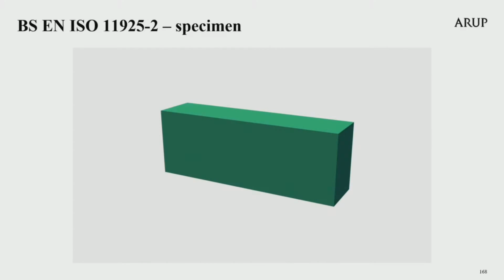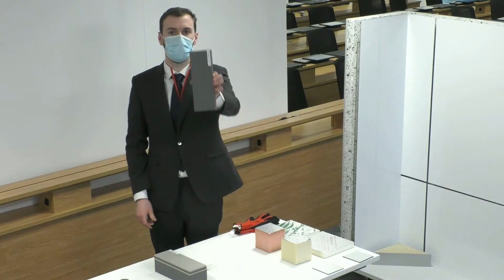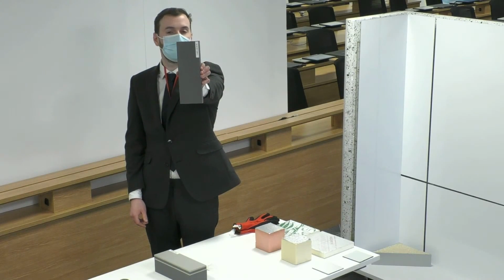A test specimen 250 millimetres long by 90 millimetres wide is prepared. The maximum permitted thickness of the specimen is 60 millimetres. A material that is normally less than 60 millimetres can therefore be tested to its full thickness, and a material that is greater than 60 millimetres should be cut down from the unexposed side to fit into the test rig. Tom is now holding up a scale replica of the test specimen.